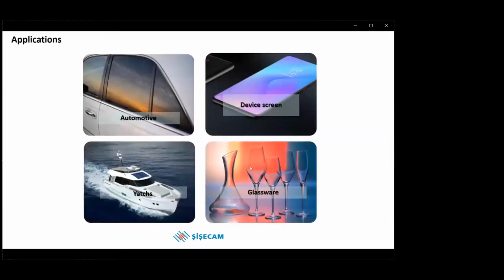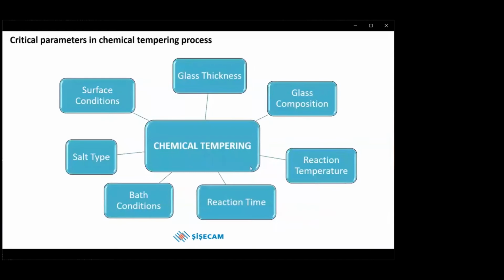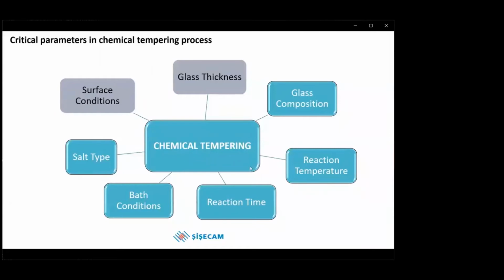The usage area of chemically tempered glasses is increasing day by day. Chemically tempered glasses can be used in automotive, luxury vehicles such as yachts, display technologies, and glasswares. There are many parameters affecting the chemical tempering process, like surface conditions, glass thickness, glass composition, reaction temperature, reaction time, bath conditions, and salt type. And in our study, we focus on glass surface conditions and glass thickness.